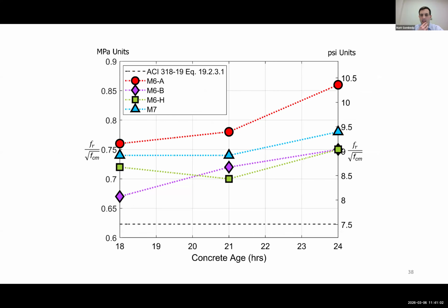And here you can see the plots. I like this chart, where you plot the modulus of rupture normalized to the square root of the compressive strength as a function of the age. We'll pay attention to the one on the right because 7.5 is the code equation. But when you look at a lot of these mixes, especially as you get closer to 24 hours, they're much